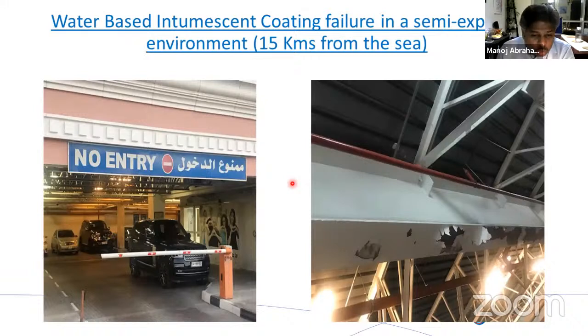All right. But what is also important is to ensure that we apply the correct coating in the correct environment. So what you see here is again a large shopping mall in Qatar. Now you will see a lot of Qatar examples because I lived about 7 years in Qatar before I moved back for my second phase of UAE. So you can see the steel inside. This is the close-up shot. The steel, they said, oh, it is internal, nothing to worry, it's internal. And they applied a water-based intumescent.